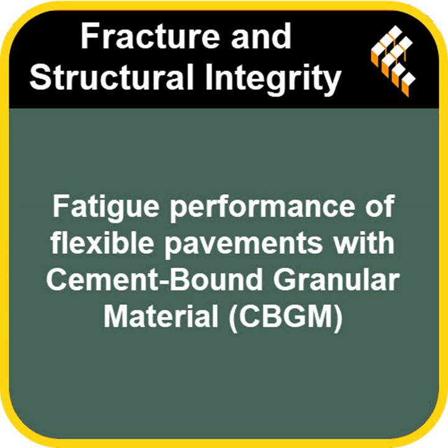Right. The researchers used BISAR 3.0 software. It's a widely used tool for this kind of mechanistic pavement design. They used it to calculate the stresses and strains for a specific CBGM layer. It was a C1.5/2 layer, that common type, with a compressive strength of 2.4 MPa. And they simulated a standard wheel load of 50 kilonewton over it. 50 kilonewton, it's like a heavily loaded truck axle wheel. Roughly, yes. It's a standard load used in these calculations. They then applied both Dempsey's and De Beer's criteria to 4 different pavement layer configurations. These varied in terms of layer thicknesses and the strength of the underlying ground, the subgrade.